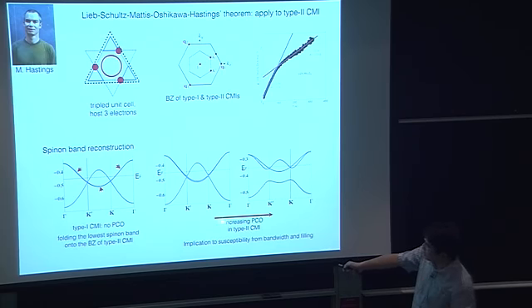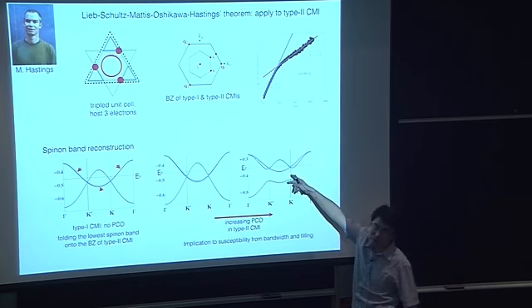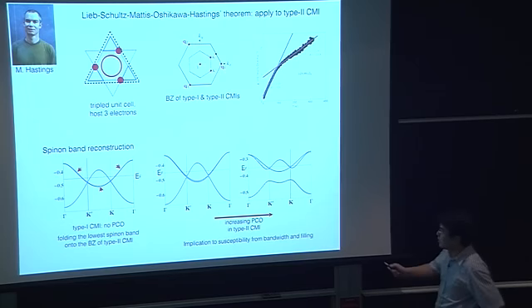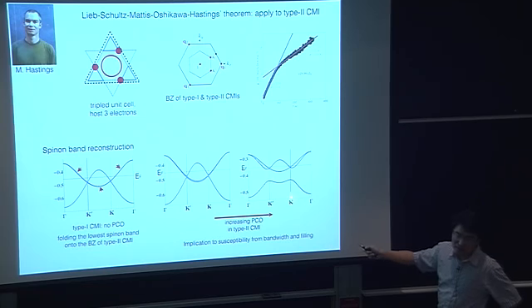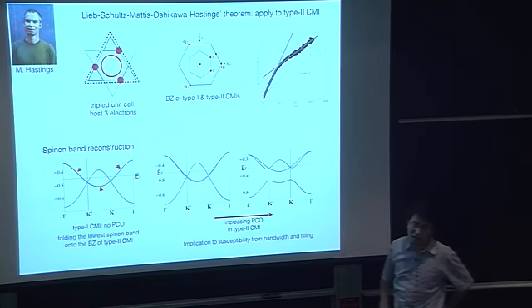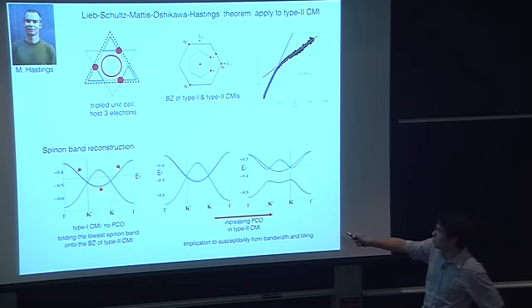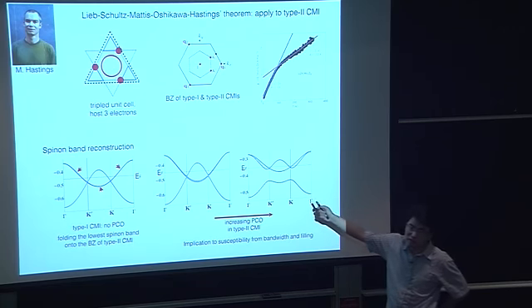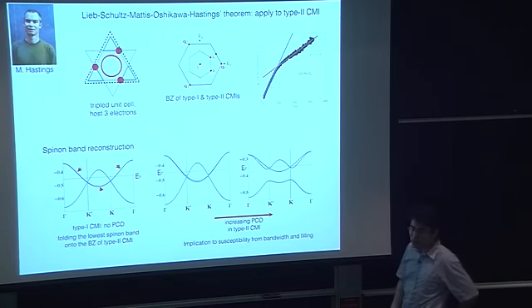Now we introduce a plaquette charge order. This doubly degenerate band structure will start to split, and then they open up a direct band gap. If I further increase the plaquette charge order, the direct band gap becomes bigger and bigger, and eventually the lowest band will be completely filled. If you count the number of spinons, 2/3 of the spinons will completely fill the lowest band, and 1/3 of the spinons will partially occupy the upper 2 bands and form a spinon Fermi surface. So that's the ground state property.